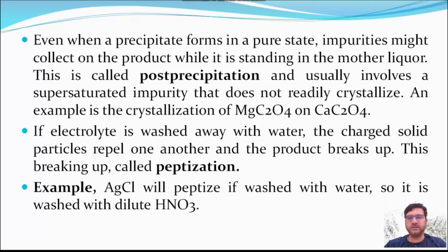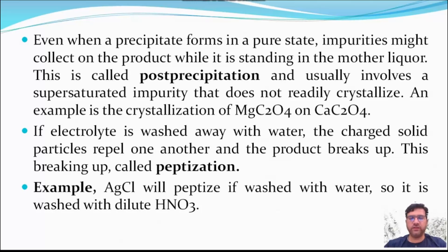Even when a precipitate forms in a pure state, impurities might collect on the product while standing in the mother liquor. This is known as post-precipitation. If electrolyte is washed away with water, the charged solid particles repel one another and the product breaks up. This breaking up is known as peptization. For example, silver chloride will peptize if washed with water, so it is washed with dilute nitric acid.